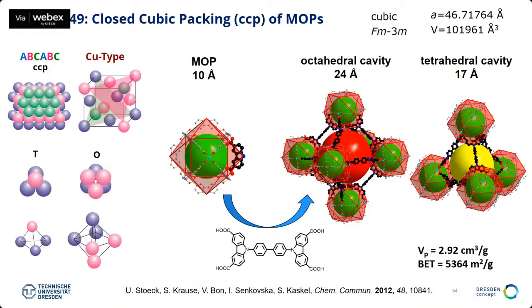And many inorganic chemists like to use the model of the close packings to explain other structures like oxide structures. Because in between the metal spheres we have holes, which are tetrahedral and octahedral holes, and oxygen can go inside, or nitrogen, or hydrogen, and so on. And this is the same architecture, so cubic symmetry. But now the metal atoms are substituted by these MOPs, and the octahedral holes are not 1 or 3 angstrom in diameter, but they are 24 angstrom in diameter, and the tetrahedral holes are 17 angstrom in diameter. So they're huge, and a lot of molecules can fit inside.